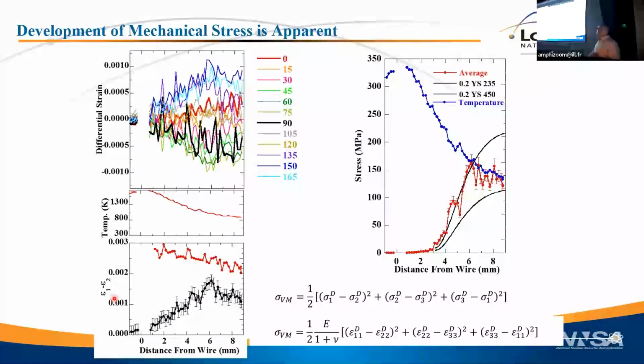And you can plot out here now what that stress looks like. The red data here is what I would calculate the von Mises stress to be. The blue data is what the temperature is doing. These two black lines are bounding, depending on the details of how you make the steel. This would be the upper bound for the yield point of the steel as a function of temperature, and this would be the lower bound.